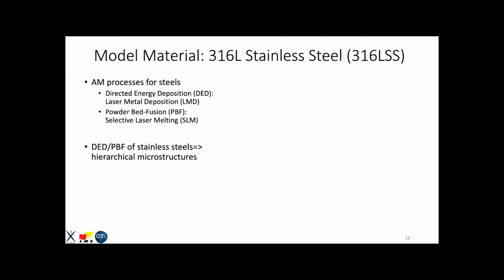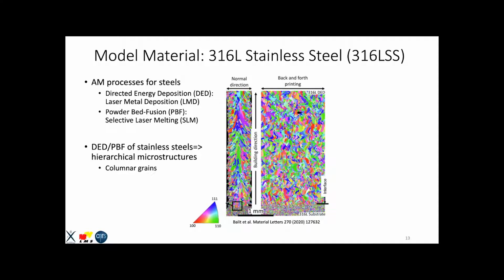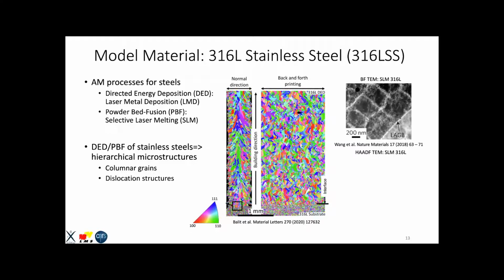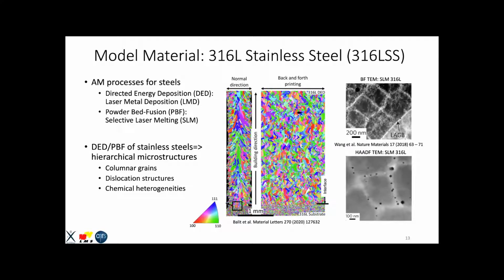And in both cases, we have hierarchical microstructures. At the polycrystalline level, we have columnar grains. So here is an example of a back and forth printing with this being the building direction. And you can see the grains quite well. There are some columnar grains with some bunches of equiaxed in between. At the intragranular level, if we zoom in, we have some dislocation structures that are formed, and they quite often overlap with chemical heterogeneities that are inside. So you have here microsegregations and some precipitates.